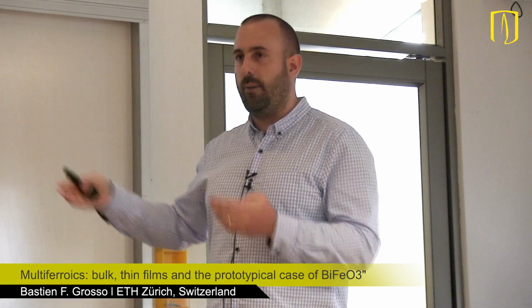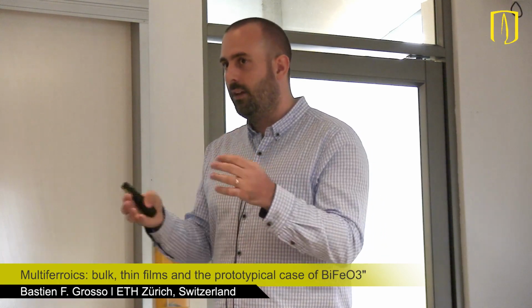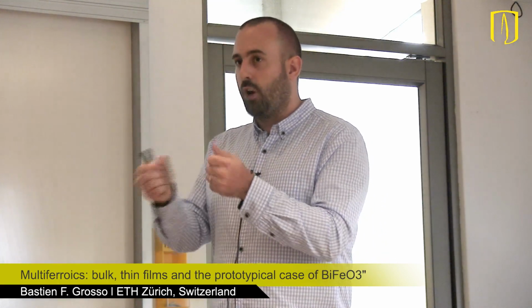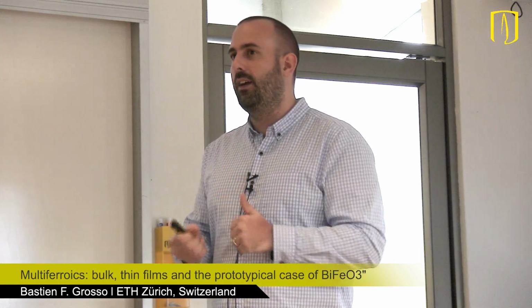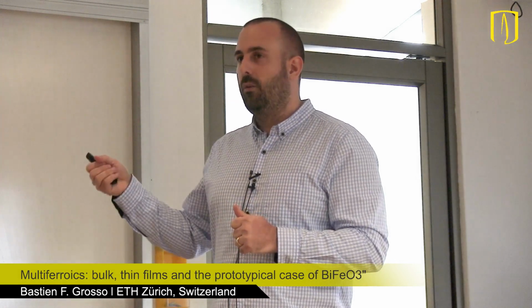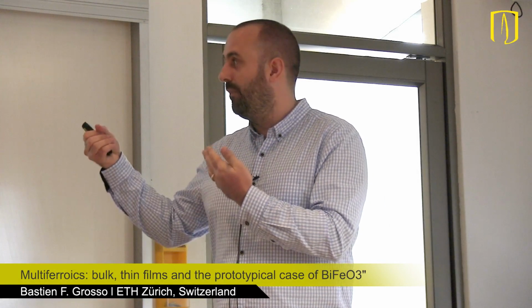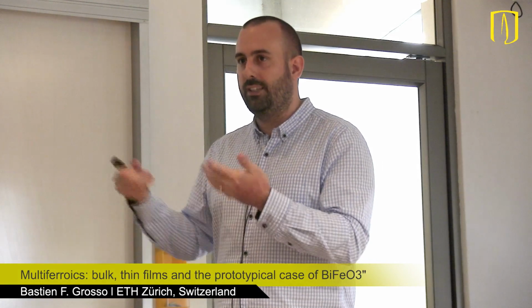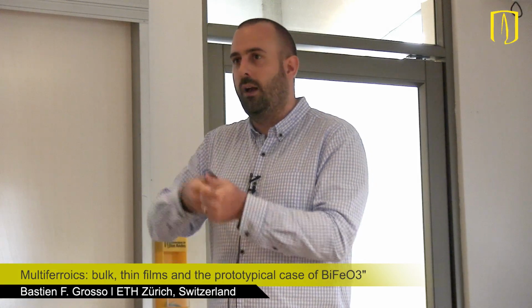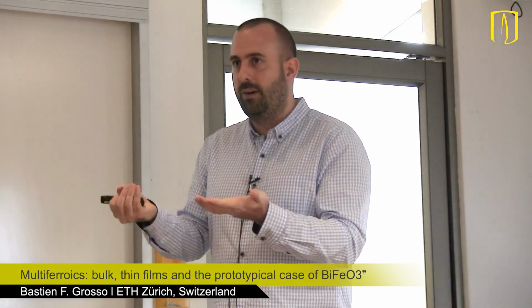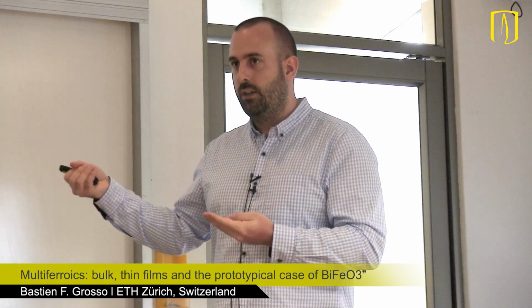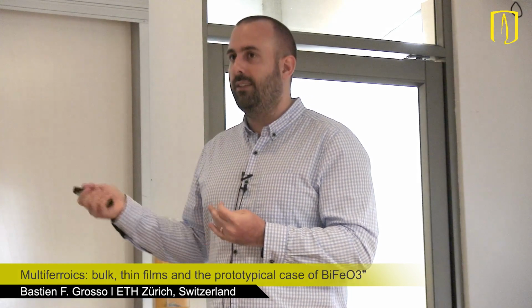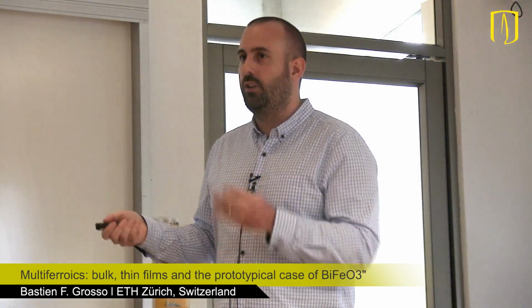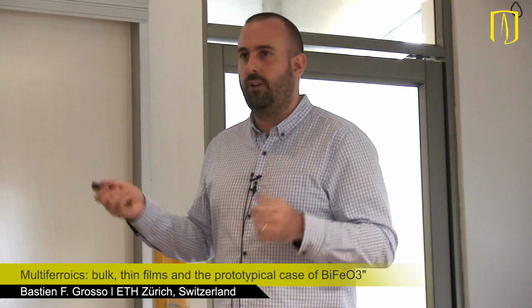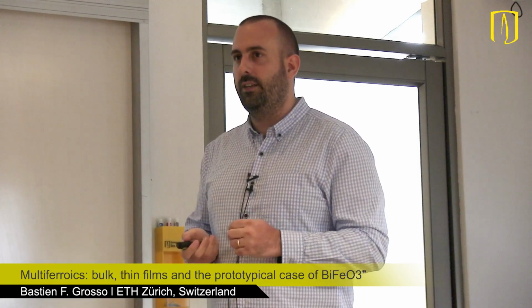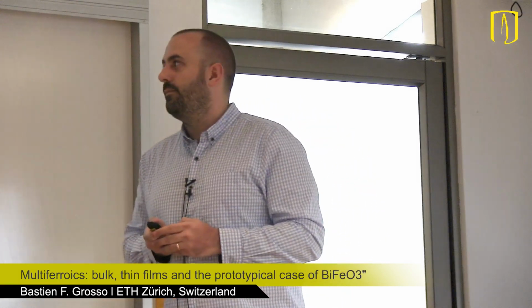An interesting thing that could happen is maybe the motivation of your question is magnetoelectricity. So the coupling between the field and the magnetic moment, and that's what we studied by symmetry, and we didn't find that it could be allowed to have something different. I mean, a linear order is not allowed by symmetry for this structure. And experimentally, there were measurements, but they are still doing some measurements. So it could be that there is something, but I don't have an answer of what is happening yet. Yeah.